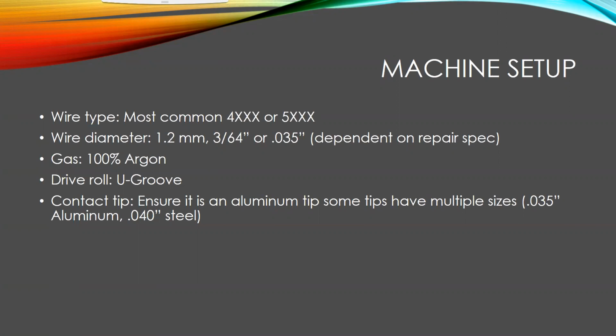And then when it comes to contact tips for setting up for GMAW aluminum, typically when you go to grab a contact tip, there's typically one size on it. So you might see 035 contact tip, you might think, oh, well, that works for aluminum, it works for steel, it works for stainless steel, everything. But actually what you need to look at is there are specific contact tips for aluminum. And typically they're oversized just a little bit, because as that wire is going to heat up, it's going to fluctuate in size and diameter just a little bit. So for example, you might have an 035 size contact tip for aluminum, and it might also be for steel, but it'll say for 040 diameter steel. Something to keep in mind.